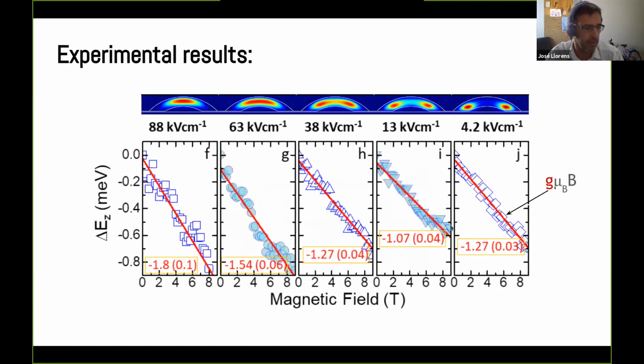And this is basically the main experimental result. Here what we saw is the Zeeman splitting that has been recorded for magnetic fields up to 9 and minus 9 Teslas, comparing the change in the main peak. And this is the fitting. There's a linear fit that follows the Zeeman Hamiltonian. And what we found is that by changing the applied voltage, we change the electric field. Also, we suspect that we are moving the wave function in this way.